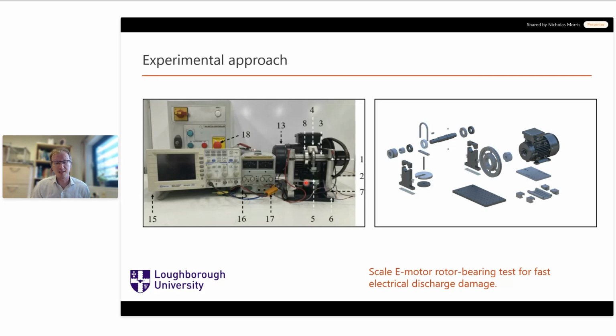And these e-machines can go up to roughly 20,000 RPM, but common urban, extra urban driving might be in the region of 7,000 to 10,000 RPM speeds. And so this test rig can go up to 9,000 RPM. We've scaled it. So this is the test rig there, you can see it is much smaller than an electric vehicle motor, so it can be easily used by a single person. And the parameter that we kept the same as those predicted to be on the electric vehicle was the film thickness in the conjunction. And we'll cover why we did that in the next slide. So we used scaled bearings, scaled loads, scaled eccentric loads to replicate what's happening on an e-machine.